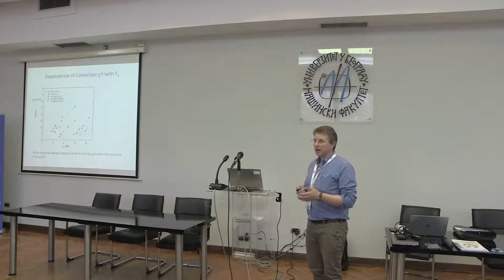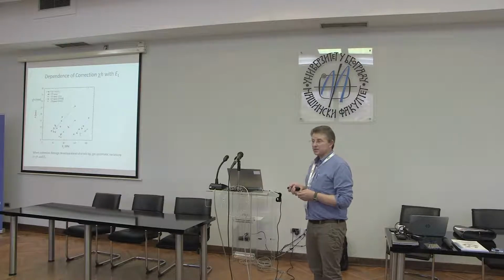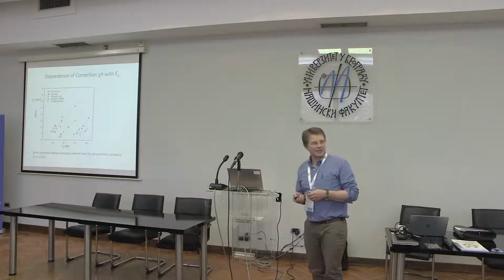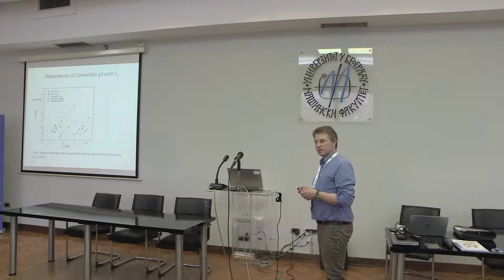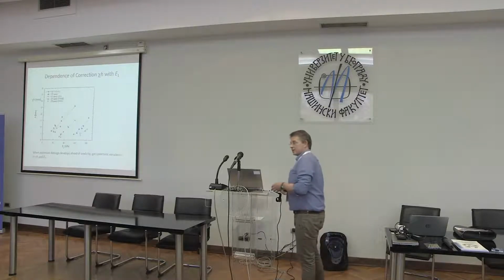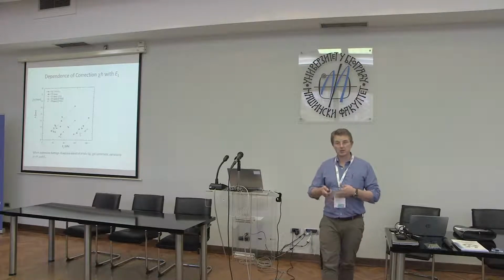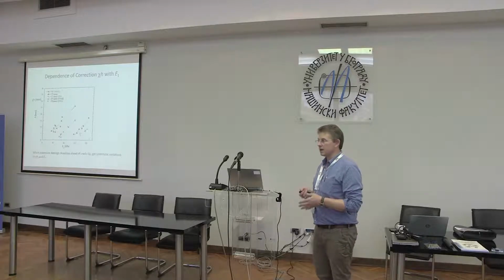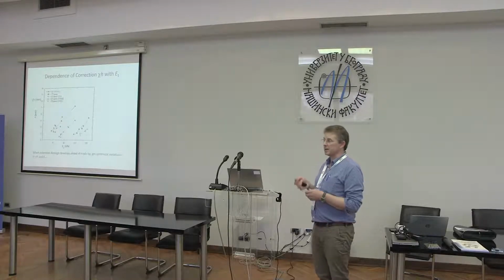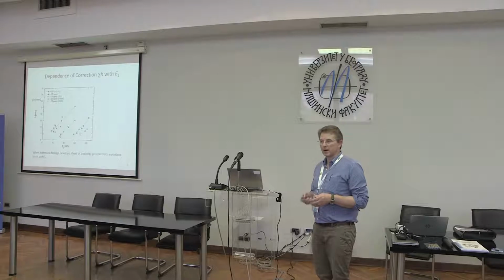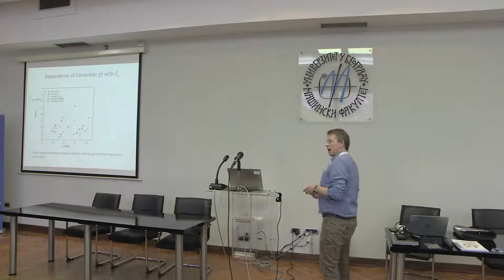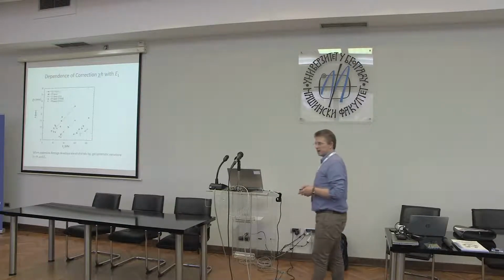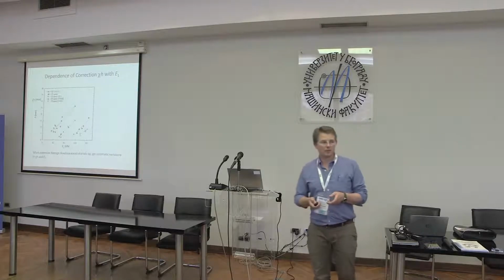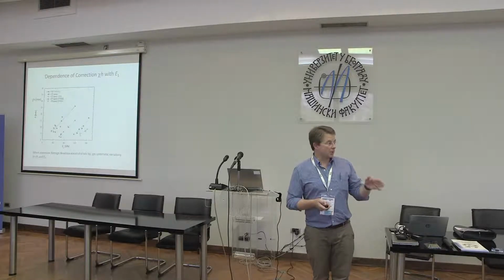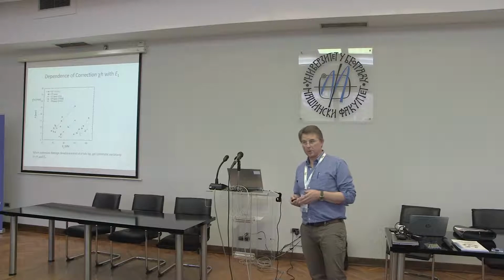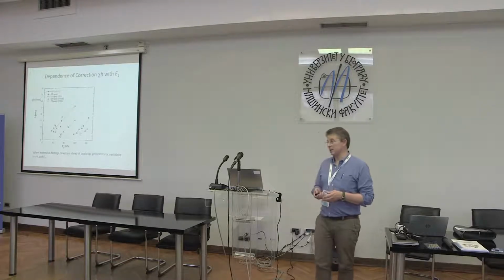If you have a very well behaved fracture, it's relatively easy to see where the crack tip is. The more complicated the fracture gets, the more difficult it becomes to actually see where the crack is, and you have a systematic problem in interpreting where the crack is. This is not just a random variation, it's a systematic variation, particularly when you have what I'll describe as discontinuous growth ahead of the main crack. And you need a way of dealing with that.